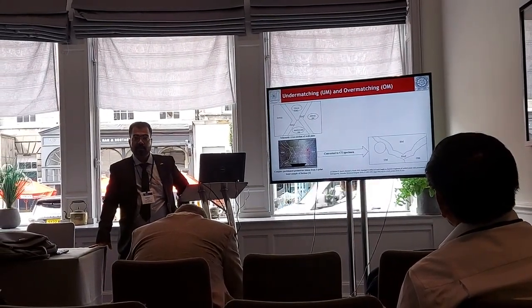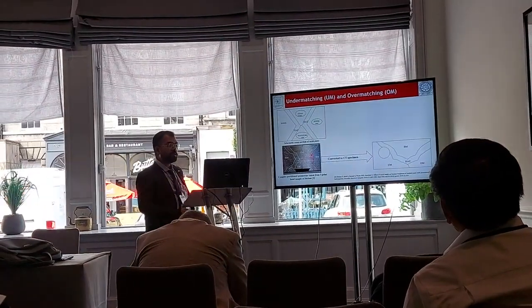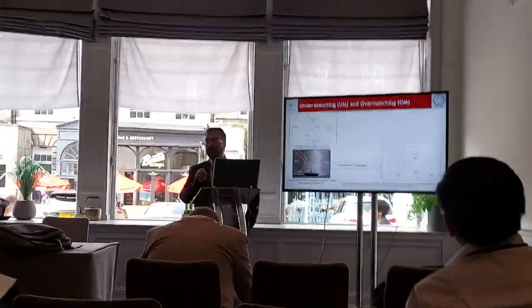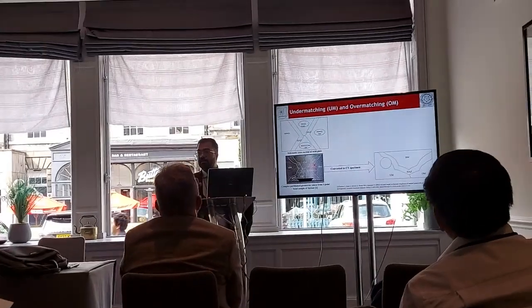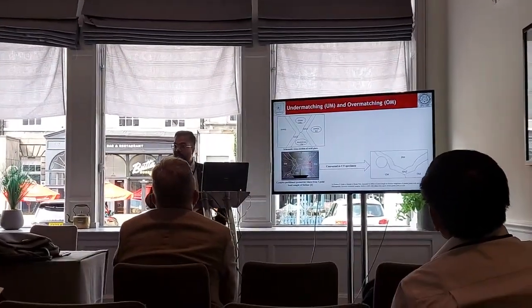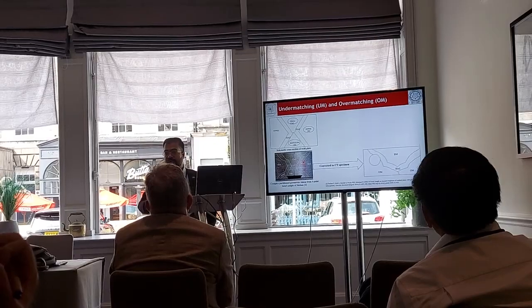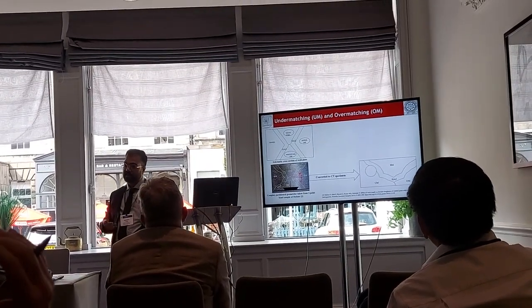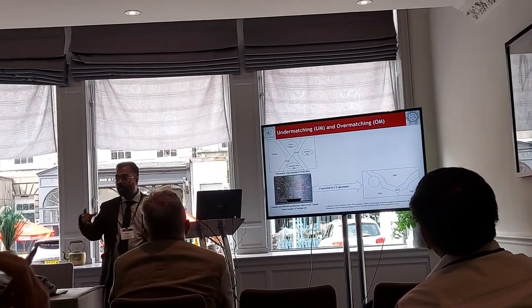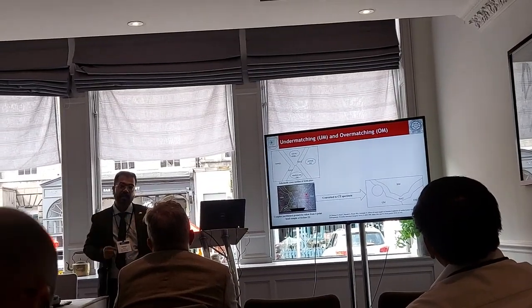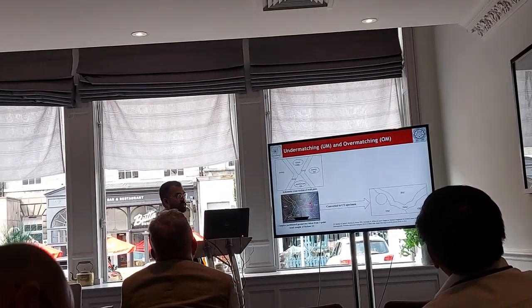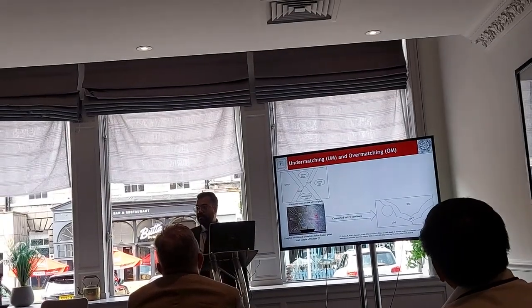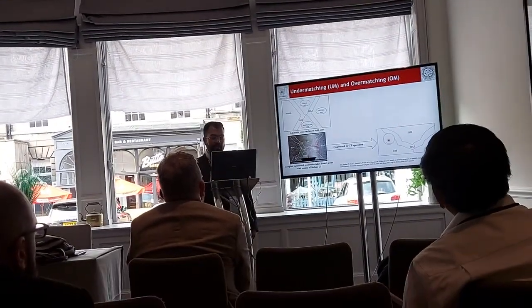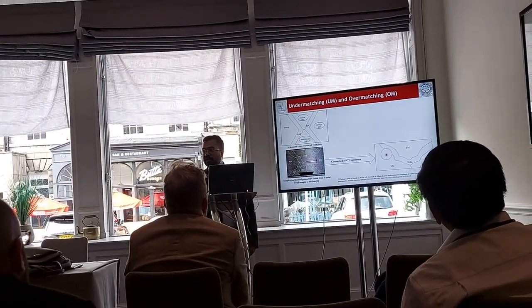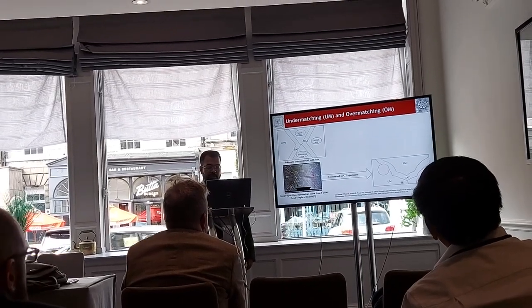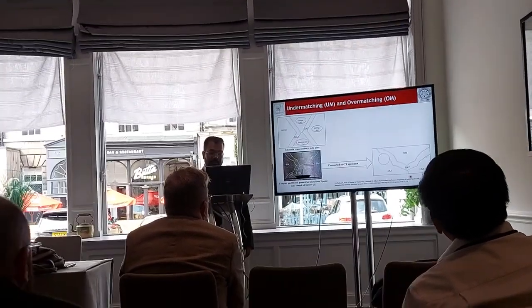They are curved. So we took that geometry and that information and changed it to a CT specimen of the same dimension. Why did we do that? So that finite element analysis can be easier, because we don't have to model rigid pins on a 3-point bend and contact and all those things. In the CT specimen, we don't put a pin in the finite element analysis. We kinematically couple this hole with a reference point and apply the boundary condition on that. So this plane will be y-symmetric.